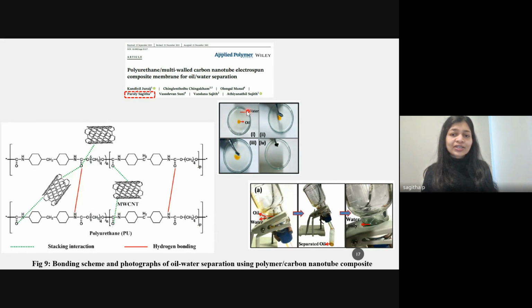So this petri dish contains water and oil. Oil is recognized, or just to understand which is oil, we made it with some color. And what we can see is that when we try to wipe out the oil using our super adsorbing, super hydrophobic membrane, it could absorb the oil selectively from the water mixture. And also we could see that it can separate the oil-water mixture, and we can get the oil and water separately using this membrane. So multi-walled carbon nanotubes can also be used for developing super hydrophobic surfaces.